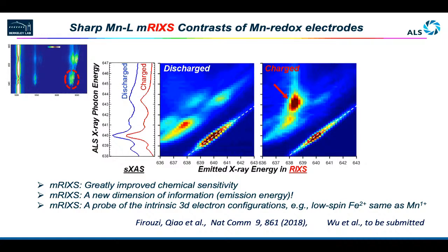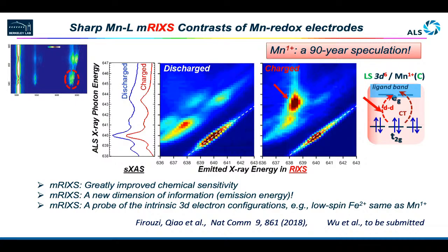So those d to d changes correspond to the occupation of your electrons, of course, and again to the spin state. And these are the low spin state of manganese 2+ originally, and 1+ will have 6 electrons over here. So this is a fingerprint of the 3d in octahedral configuration, low spin, with all the 5 electrons occupied. So the majority of the d to d is from the t2g to eg. While if you remove an electron, you will have extra t2g occupied to t2g unoccupied excitation. That's why you see 2 lines, and the other one is more concentrated at the higher energy dd excitation.